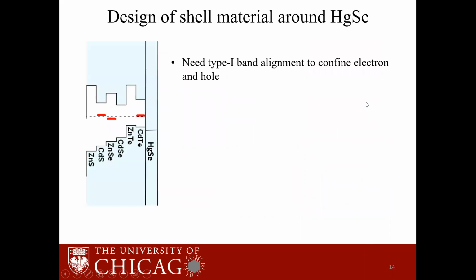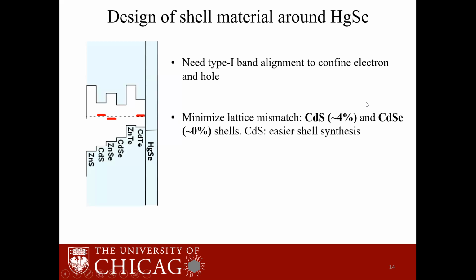growing the shell. The most important property of the shell is that it should have a type 1 band alignment, which means that the conduction band of the shell should be higher than the conduction band of the core, and the valence band of the shell should be lower than the valence band of the core. A second requirement that we have synthetically is that the crystal structure of the shell should be the same as the crystal structure of the core, and the lattice constant of the shell and the core should be similar to minimize strain between the two materials. The two shell candidate materials which satisfy these criteria and are easy to synthesize are cadmium sulfide and cadmium selenide.